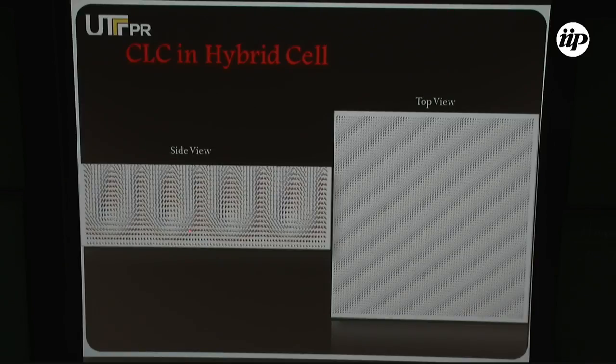You get this undulation where you have kind of a perpendicular direction here of the helical axis. And you see below here you have some space where the material is still planar. So what happens here, if you try to change the pitch, this elastic boundary here tries to rotate, and as you change the pitch, the whole thing has to rotate. And if you see from the side view, it should look like this, and when you look from the top, it looks just like this.